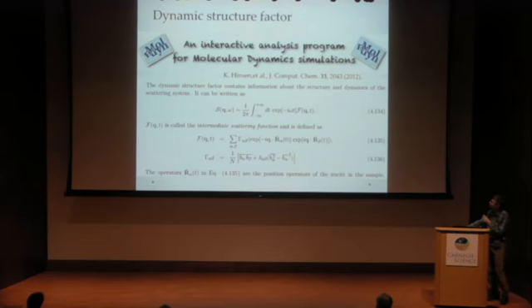And you can even take one line like that and look in time, over a longer time. The simulation was run over 100 picoseconds, but I showed just a piece of it. And you see that these clusters appear and disappear, appear and disappear. So they are more or less random. You don't see any area where it would stay for a longer time. So that's why when you average for longer than a few picoseconds, you lose the information about the clusters. Now we can do even more.